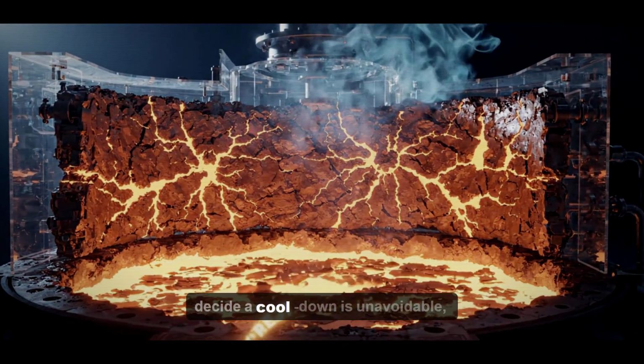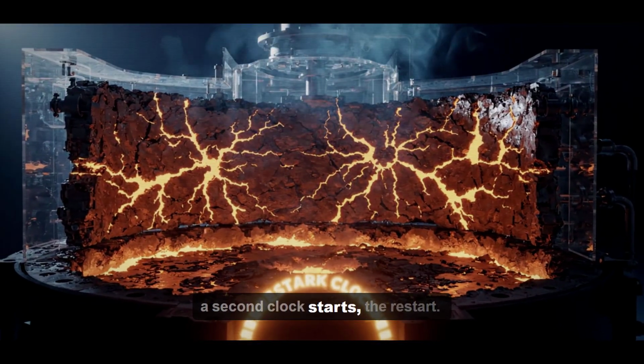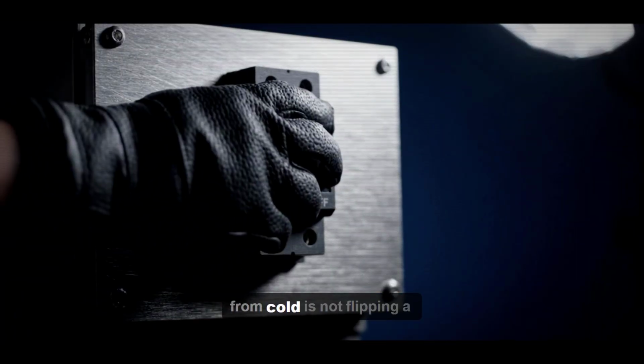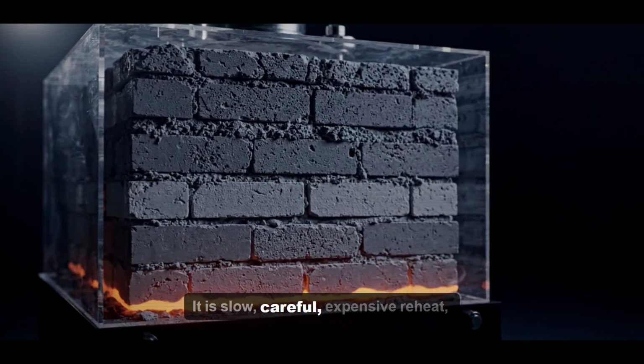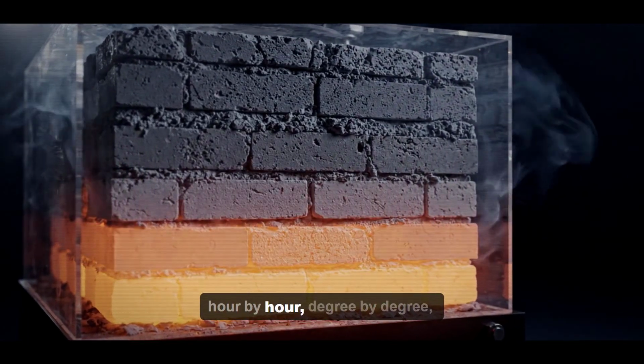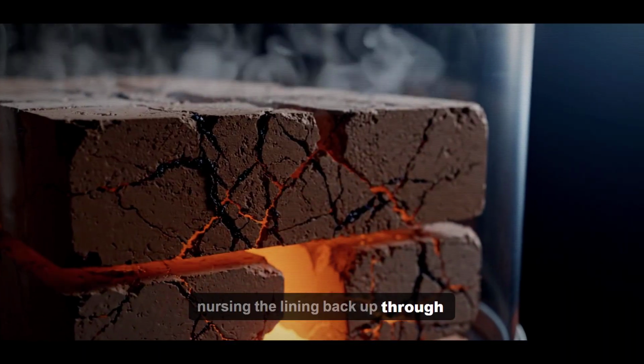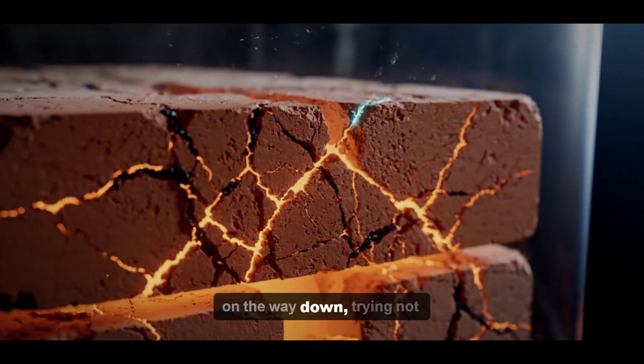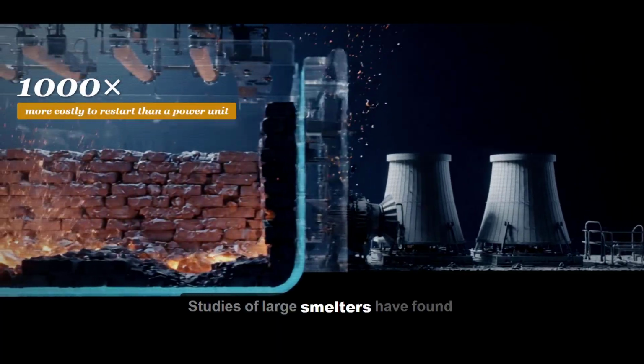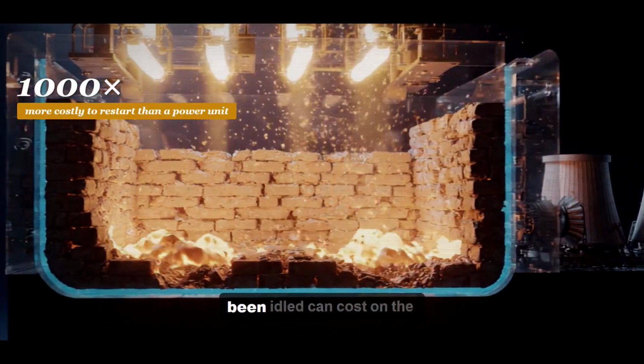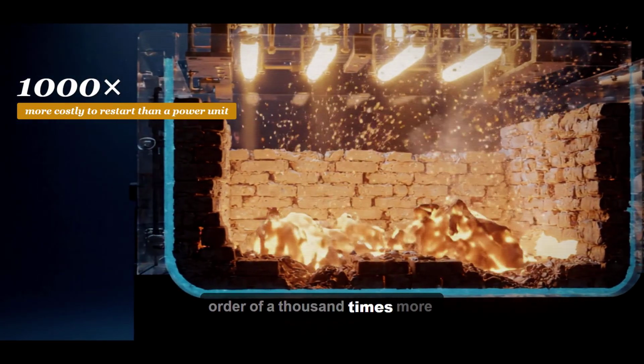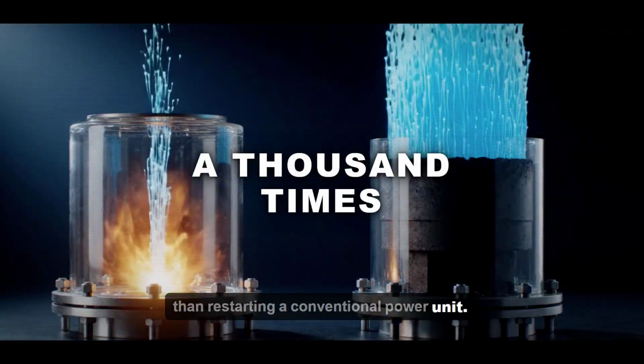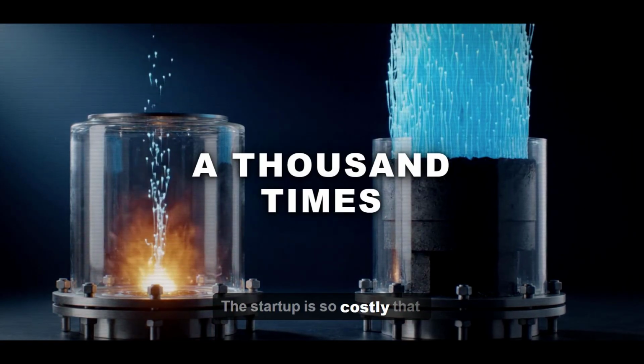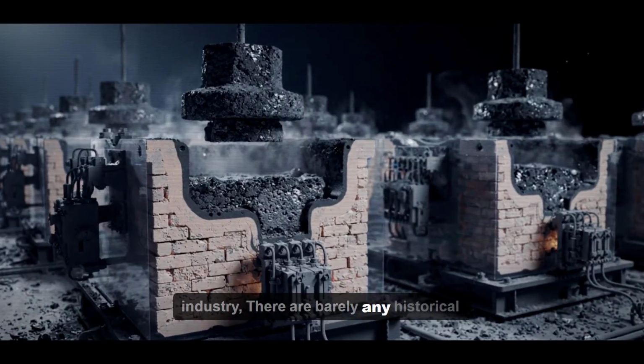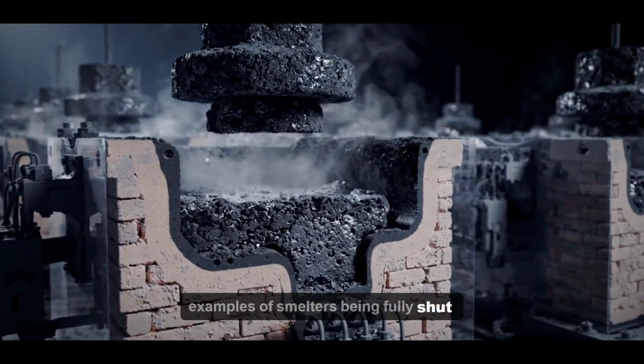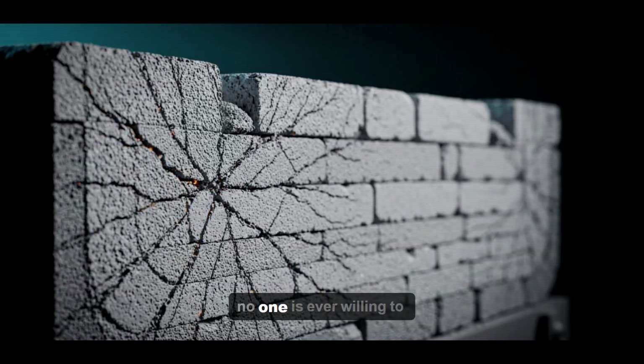because the moment you decide a cooldown is unavoidable, a second clock starts, the restart. Bringing one of these machines back from cold is not flipping a switch. It is a slow, careful, expensive reheat, hour by hour, degree by degree, nursing the lining back up through the same temperatures that damaged it on the way down, trying not to shock it again. Studies of large smelters have found that restarting one after it has been idled can cost on the order of 1,000 times more than restarting a conventional power unit. 1,000 times. The startup is so costly that in some parts of the metals industry, there are barely any historical examples of smelters being fully shut down and restarted, simply because almost no one is ever willing to do it.